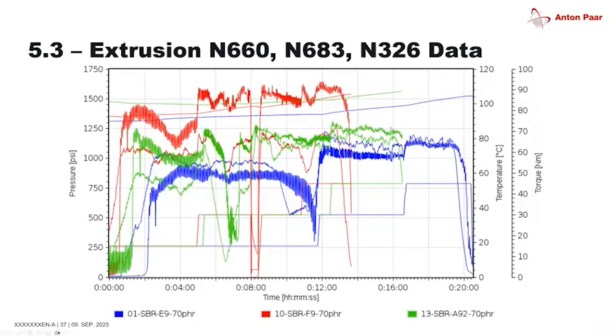This is now, again, it's not art, it's the art of extrusion rheology. We have again the three steps, but this is now taking into consideration everything at 70 PHR: the high structure, the low structure, and the middle of the line. The middle of the line is our E9. So this is the blue curve, and the high structure is the red with the highest pressures and highest torques, while the low structure is the green. So we have some interesting results, but again,